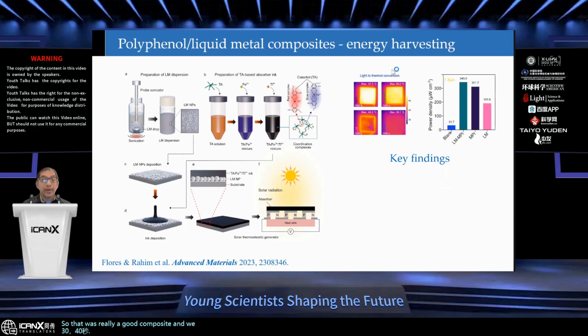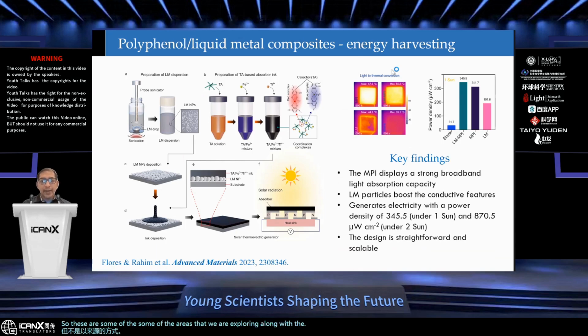And we in fact made a record, this 345.5 that I show on the right-hand side. It's possibly twice or thrice that of any other solar thermoelectric generator at that point in time. So it was quite good. We are still exploring this area of solar energy harvesting, but not in the manner of solar cells. These are some of the areas that we are exploring along with the catalysis field. These are the key findings of that paper: if we think smartly enough, there is a lot that can be done in the composite area too.